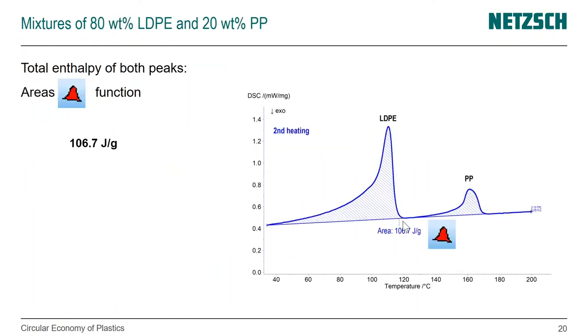better. So I have the LDPE material that has potentially a filler in it. So the area here would be smaller than the area of an LDPE of the same weight that was without any fillers. So based on the area of your material with fillers, you can also compute the amount of material that you have in there. It's typically done like that.